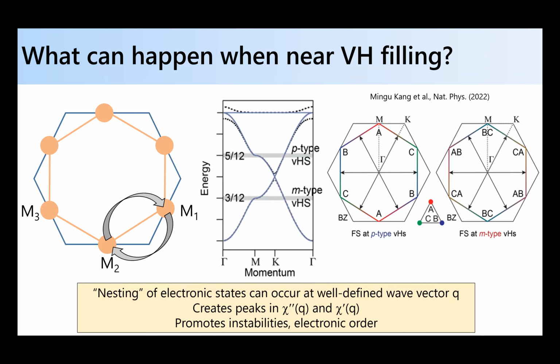Okay, so why is tuning the filling near a Van Hove point interesting? First off, you can have nesting between these points at the Fermi level. If you can tune the Fermi level to the Van Hove point, you just have a series of points which can be connected by a well-defined wave vector, and so this can promote instabilities along this wave vector and create peaks, for instance, in the Lindhard susceptibilities, in the real and imaginary components.